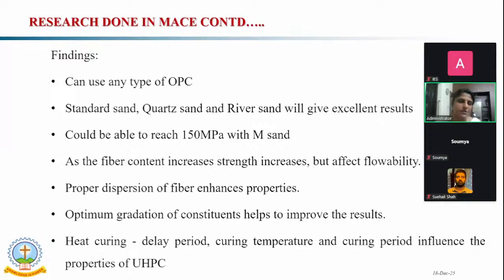So we have considered 20 mm straight steel fibers with 0.2 mm diameter, and we compared that with 13 mm long fibers with 0.2 mm diameter. From all the studies, we concluded that 2% of 13 mm fibers will show the same results as 1.5% of 20 mm straight steel fibers. Then optimum gradation of constituents helps to improve the results. We have considered the Puntke test as well as the MR software. In the case of heat curing, we have considered different delay periods, different curing temperatures, different curing periods. That all affects the properties of UHPC. And what we follow is 90 degrees centigrade with a 48 hours delay period and a 48 hours curing period.